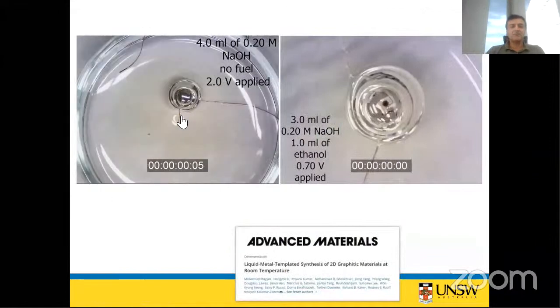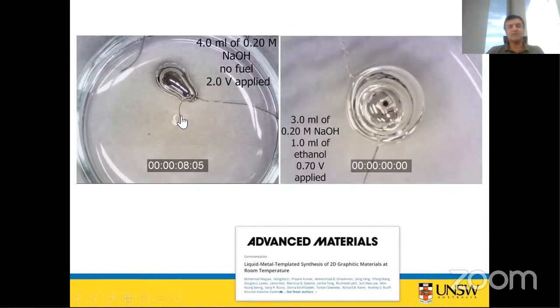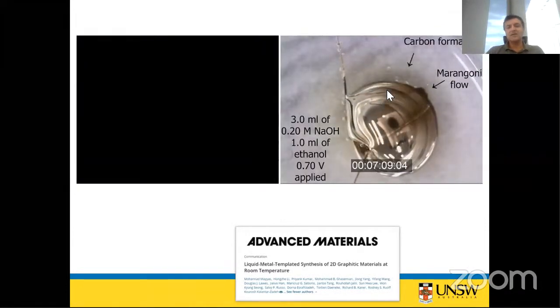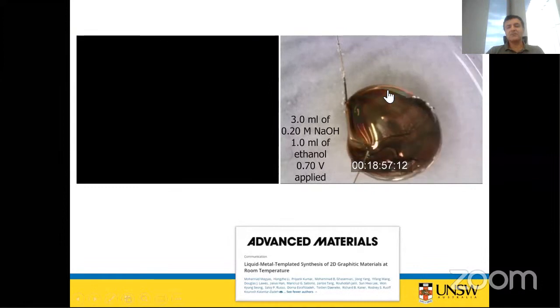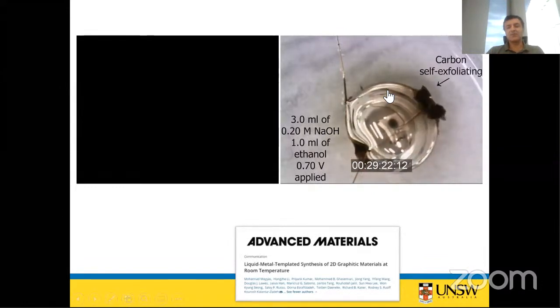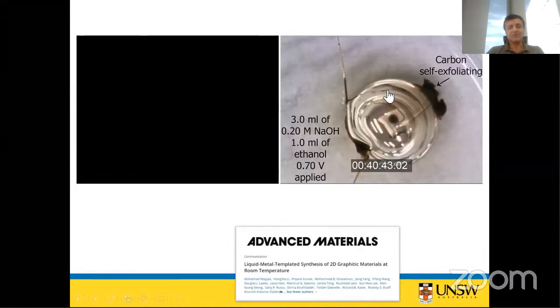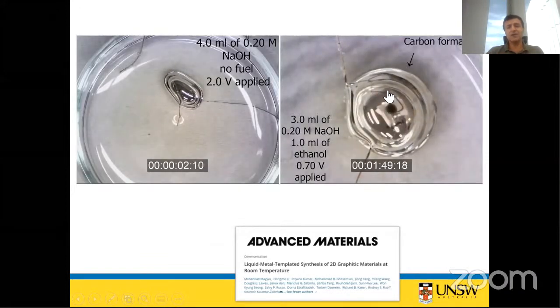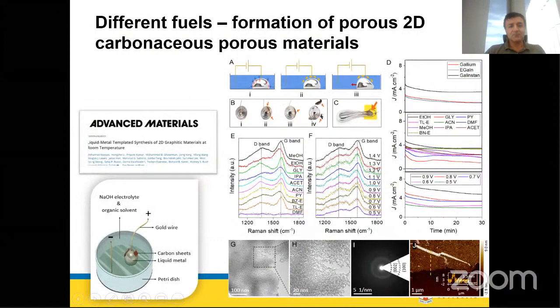Here, if you don't have a fuel, as you see, after a few minutes the liquid metal deforms, but nothing is formed on the surface. Here, you apply voltage, and you have graphitic material formed on the surface. So the graphitic material templates on the surface of the liquid metal and is two-dimensional. But what type of two-dimensional material are we creating when we are deforming liquid metal in the process?